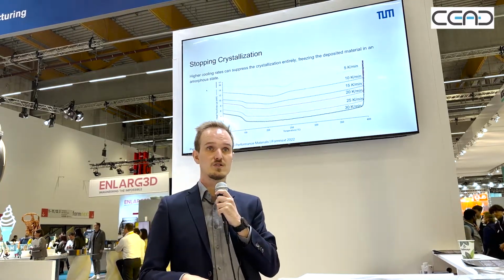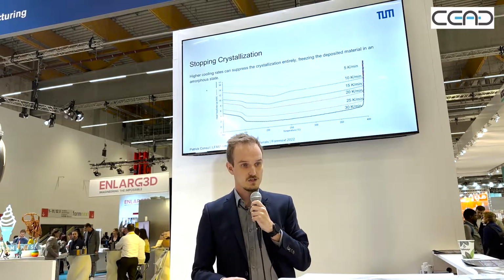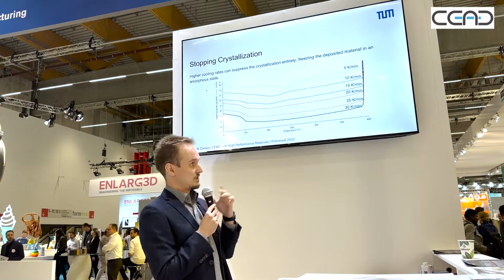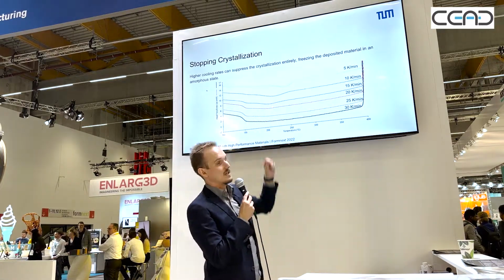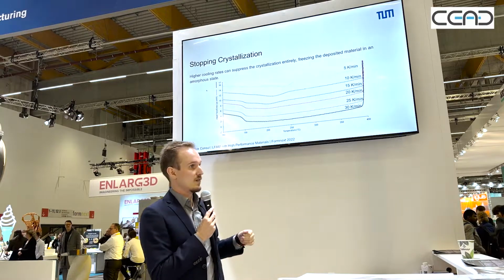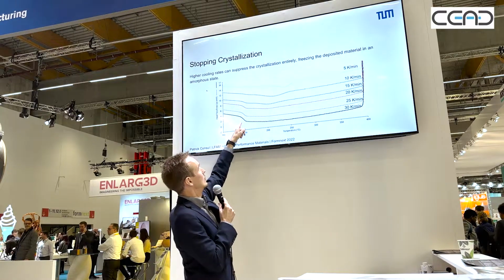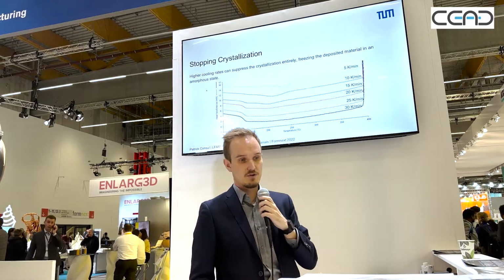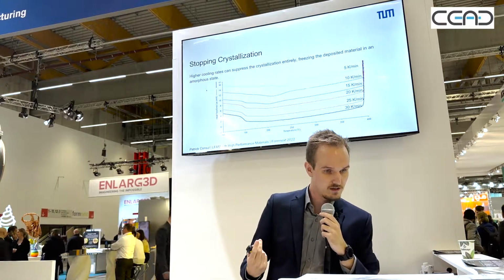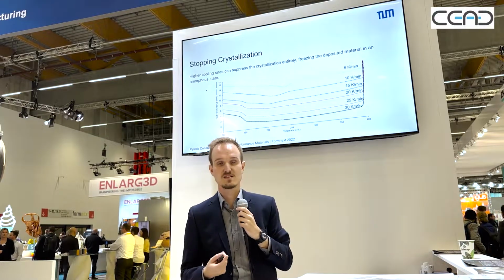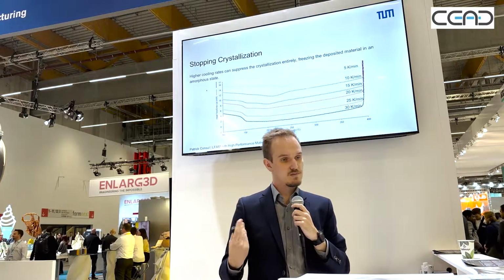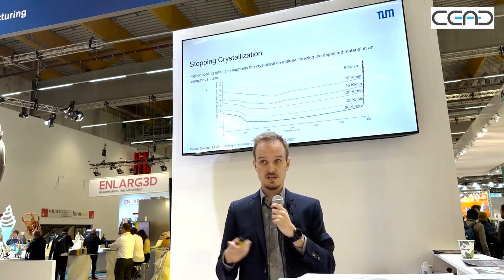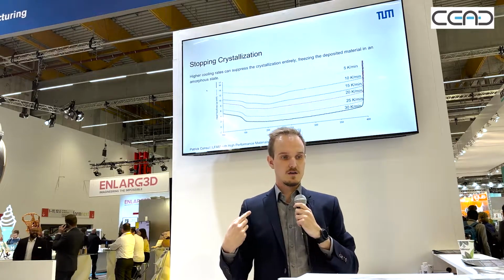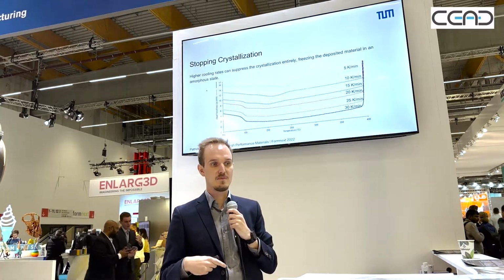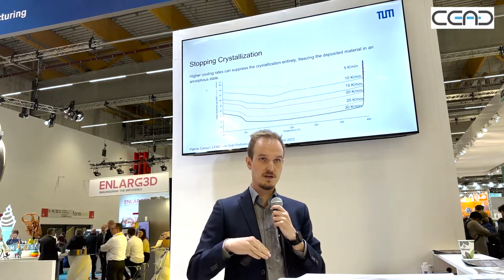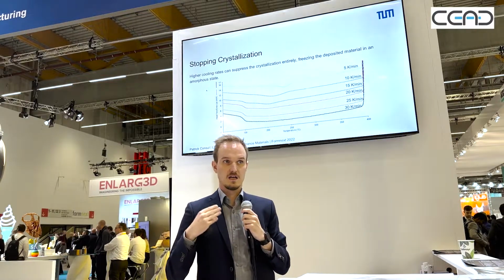you can actually completely suppress crystallization in 3D printing. So with this polymer, it's a DSC graph, and the little peak you see here is when the crystallization happens. And the more crystalline your material is, the less you see of the glass transition temperature. And basically what you can see here is that anything that's cooled quicker than 25 kelvins per minute doesn't crystallize at all, which is a speed that you can quite easily hit in 3D printing, even with the large systems. And what will happen is that once the layer is deposited, it will cool down quickly, and the surfaces will stay amorphous and bondable.